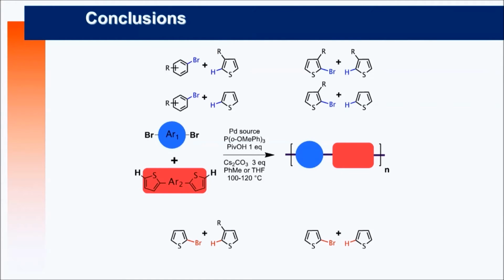You can polymerize any aryl bromo group with any CH bond on the thiophene unit. So bromo aryl, fluorene bromo, benzene bromo, carbazole bromo, what you want, on a thiophene unit, protected or not protected. If you're careful, you will get well-defined copolymers. That's what we believe. So it will replace Suzuki coupling for most cases and Stille coupling in some cases here. Limitation here: if you have the bromo on the thiophene unit which is not protected, there are some problems of selectivity. So this is still a limitation and this is still a subject of study. So I think it's good news for the field because, I repeat, it will simplify the synthesis and lower the cost.